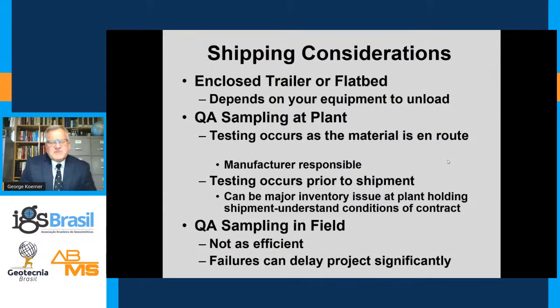Okay, now we've manufactured the material and we'd like to ship it to the site. This is typically done in enclosed trailers or flatbed trailers. It depends on the equipment for loading and unloading. I should point out to you that the QA sampling is best done at the plant. Transportation has become extremely expensive, and certainly we need to head off problems with this as soon as possible. That testing is typically the responsibility of the manufacturer, and the test occurs prior to shipping so that you can inventory and hold any material that is off spec.